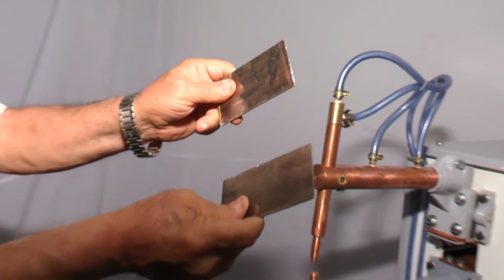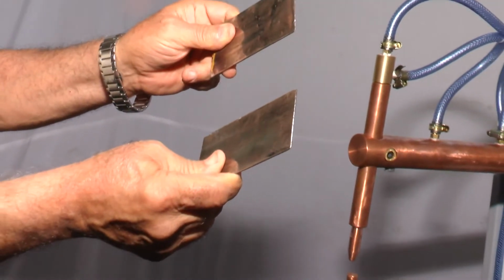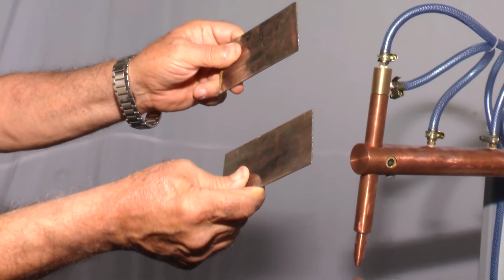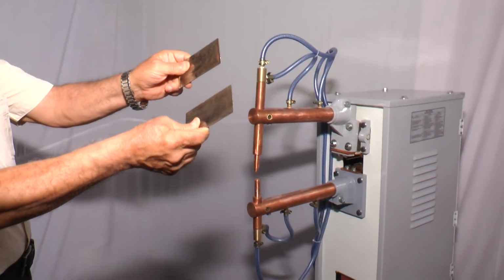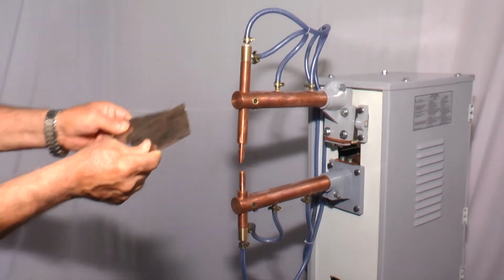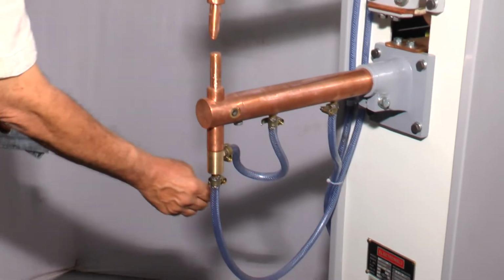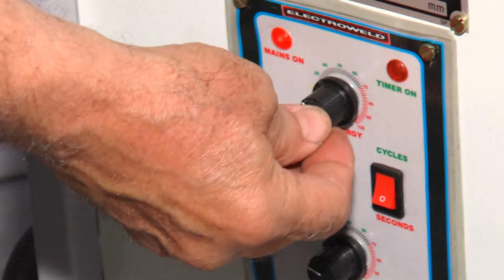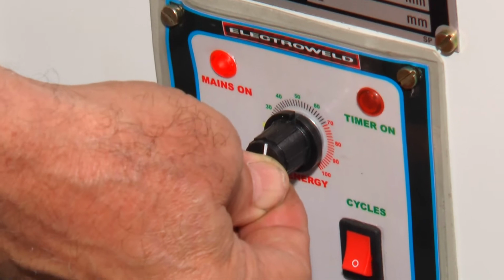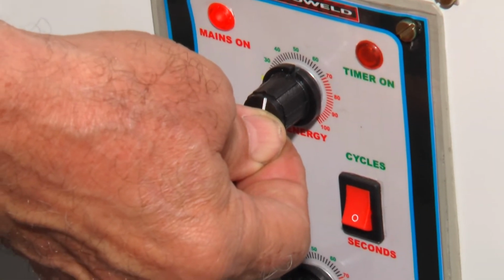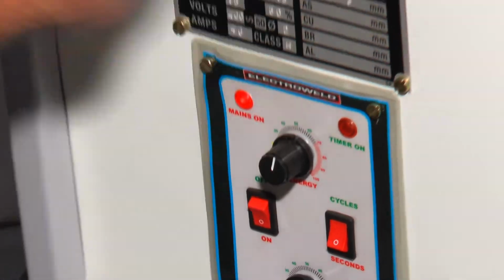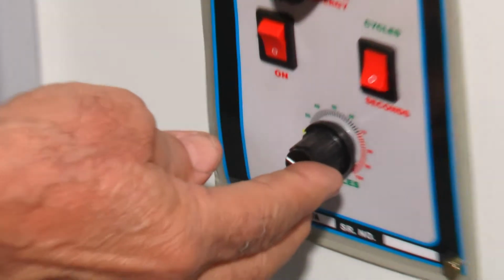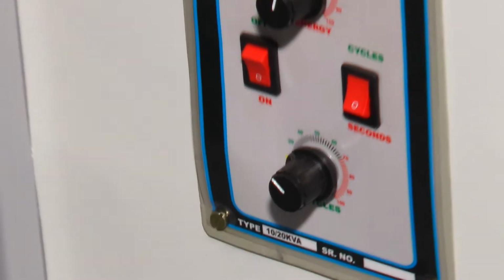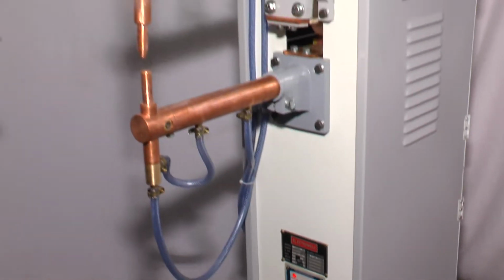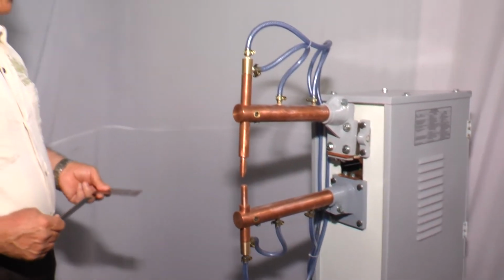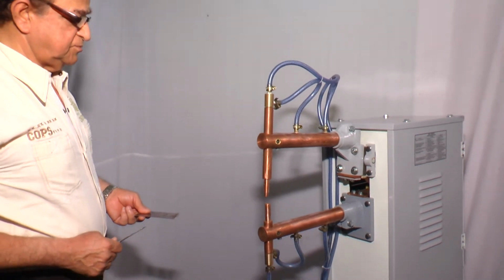Now we will show you welding of 2 mm plus 2 mm thick MS components. For this again we have to adjust the power control, say number 6, which corresponds to 60% of the duty cycle of the machine, and this weld timing keep at 15 cycles, whereas the pressure spring is provided at the back, that is pre-adjusted at our works.